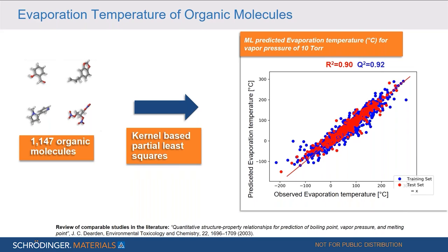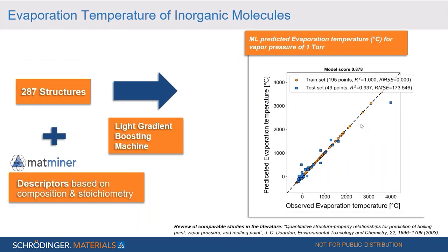In this case, this model was built using 1,147 molecules and auto QSAR. We can see the results for the evaporation temperature on the right-hand side, and they are quite good. So we have an R-square value of over 0.9 for training and test set. And in a similar fashion, the evaporation energy for inorganic compounds can be predicted using machine learning. In this example, there were only 287 structures which were utilized, together with the matminer inorganic descriptors. And we see again here we have a quite good prediction. So we have R-square values of over 0.9 if you look at the linear relationship between the observed evaporation temperature and the predicted one.